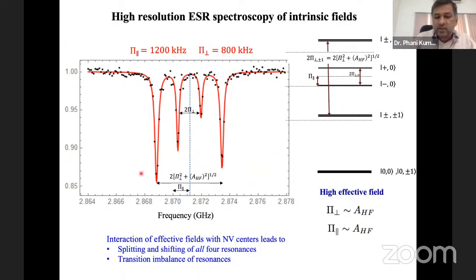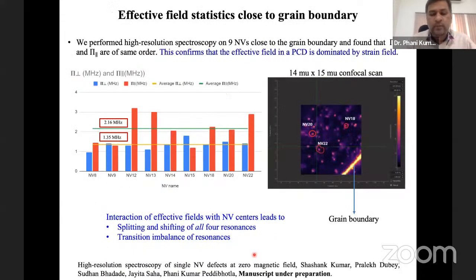And also you can see that there is a transition imbalance. This one has a larger contrast and this one has a smaller contrast, and there is an imbalance between the inner resonances and also the outer resonances. This is because of the direction of the effective field, which is oriented perpendicular to the NV axis. We have also performed detailed studies of this, but I am not discussing them here due to time constraints. And we have also confirmed that this PCD sample is mainly dominated by the stress fields. We have also done a more detailed investigation and found new insights, but we are currently preparing a manuscript reporting this work.